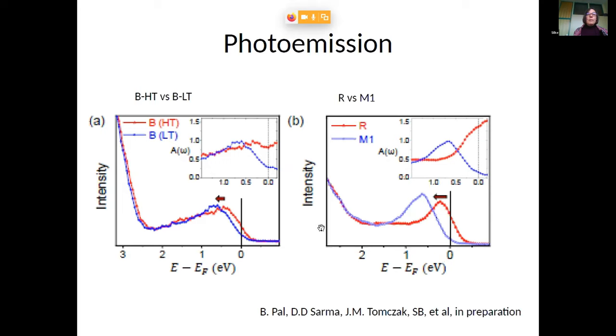Nevertheless, when you divide by the Fermi function, you have a little indication of a first difference. For the usual monoclinic and rutile phases, you have a peak at the Fermi level, and in the high temperature B phase, things are a little less peaky, and you rather have a little depletion. Nevertheless, you do clearly have spectral weight in a pronounced fashion at the Fermi level.